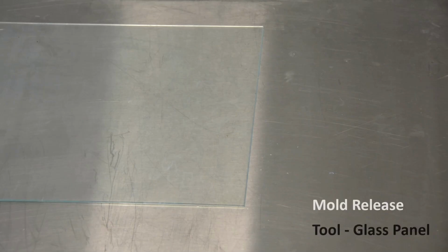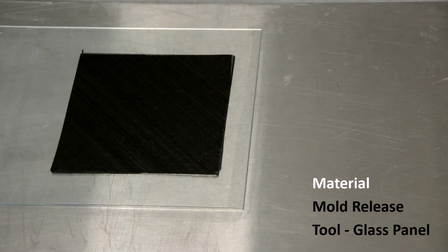We will now take a look at the parts of our layup. Our tool will be a flat sheet of glass which we will use to produce a flat carbon panel. On the tool surface, we will apply mold release to prevent the resin from adhering to the tool. Our material is unidirectional carbon fiber Prepreg consisting of HTS40 fiber and MTM45-1 resin.